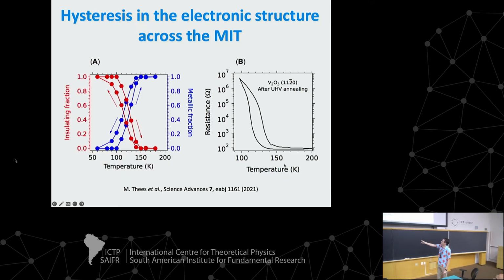The blue is the metallic fraction, and the red is the insulating fraction as a function of temperature. And as you can see, this beautifully follows the resistance measured exactly on the same thin film as we did these measurements as a function of temperature, with the same width in the temperature cycle. So this concludes what I wanted to show you.